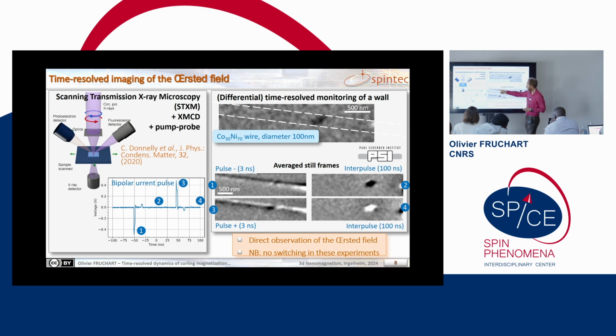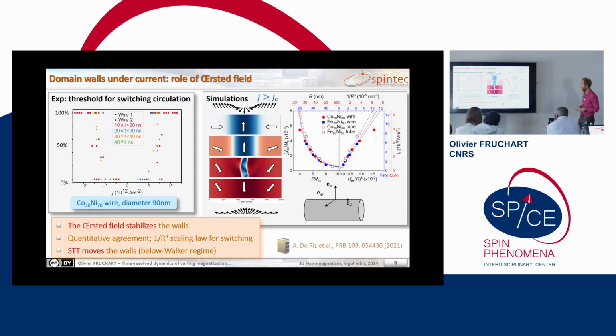And you see during the positive or negative pulse, you have a black-white or white-black contrast. And as the beam is coming perpendicular, this means that starting from longitudinal magnetization, you had some switch tilting like this or like that under the stimulus of the Ørsted field. In that case, we had some technical problems. We could not do some switching, but in other experiments, we made some switching.